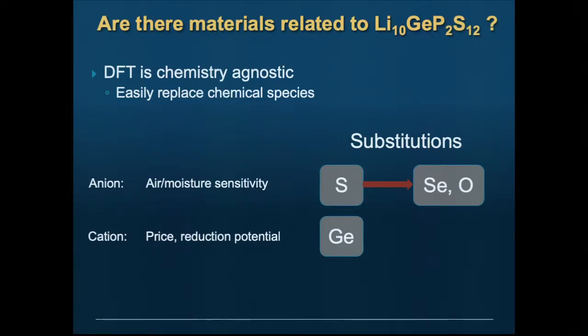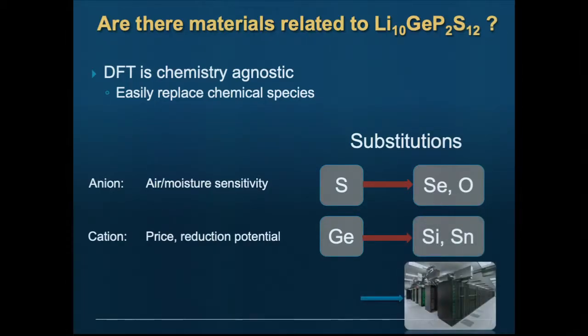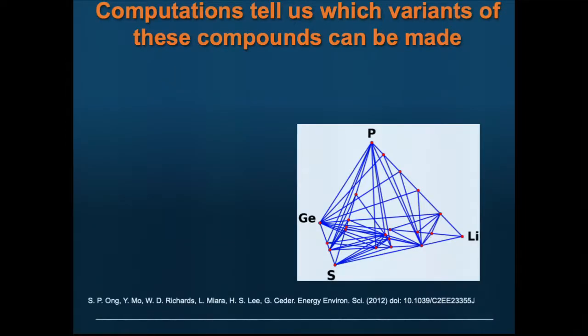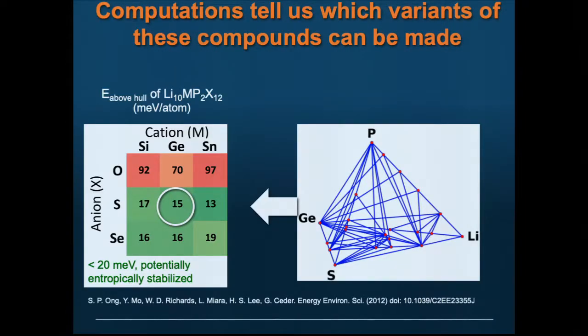So we wanted to see, could you replace it by selenium? Not that selenium is better, but if you could replace it by oxygen, that'd be awesome. And germanium is a non-starter because of price, right? And could you replace it by things in the same column, silicon or tin? So this is a great ab initio problem, because you can first look at the stability of these compounds. So we calculate the substitutions with silicon and tin, and then on the anion with oxygen and selenium. And we calculate the energy by which it's stable or metastable.